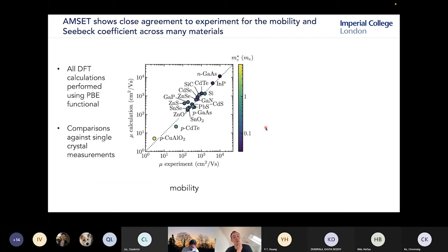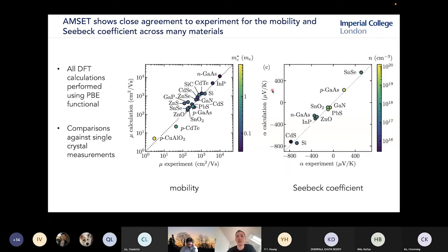We tried to screen a few more materials. Here I'm presenting a summary of 21 materials that were calculated using AMSET. I'm showing experimental mobility against calculated mobility. And again, we see very nice agreement across the board. I'd say that the electronic structures were calculated using PBE, which is a relatively cheap method. There are a couple of outliers here, and when we go to a higher level of theory to calculate the electronic structure, this gets a much more accurate effective mass, and these points drop down onto this line here.